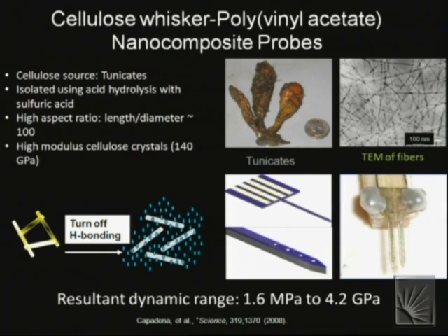When the polymer uptakes moisture, there's a change in the chemical interaction between the fibers, causing them to lose their interaction, and then the mechanical properties mimic that of the matrix polymer, which is extremely soft. And the macro group has shown that you can get a wide change in the mechanical modulus in these polymer systems. And then my group is looking to make a structure for neurointerfacing that looks somewhat like that.